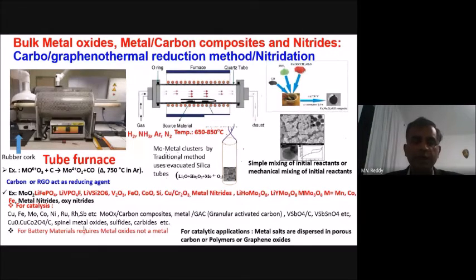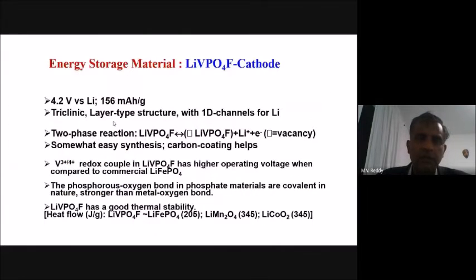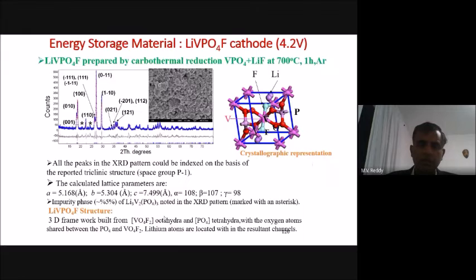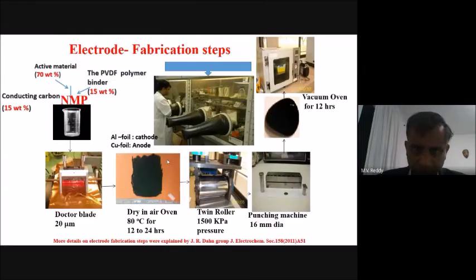Remember, sometimes people are working with catalysis or other applications where we need some metals within the carbon matrix. Accordingly, we use an appropriate amount of carbon, meaning more carbon is needed for those applications. One example is lithium vanadium fluorophosphate. It is a 4.2 volt cathode material with reasonably good thermal stability compared to lithium cobalt oxide, really good, and close to lithium iron phosphate. These are typical XRD patterns showing the triclinic structure. By using the software we know what type of structure it is, and based on that we can calculate the lattice parameters, etc.